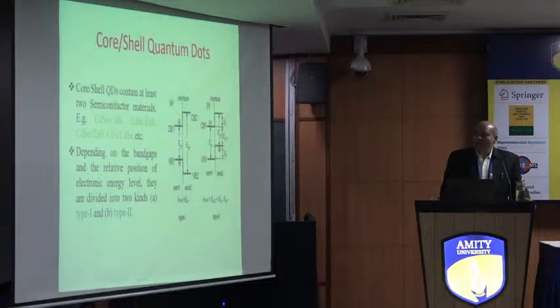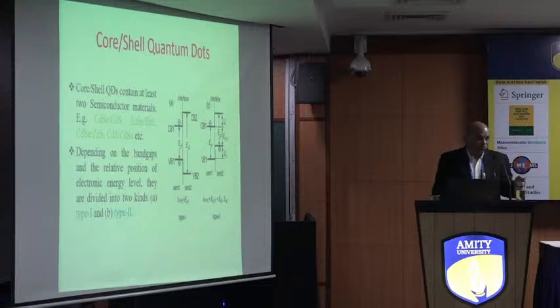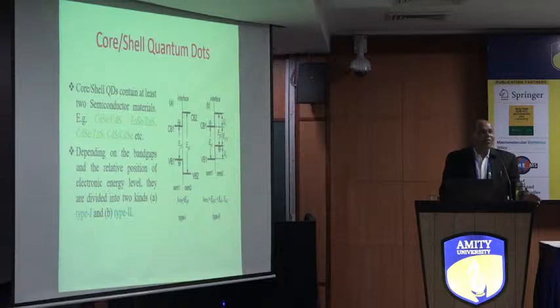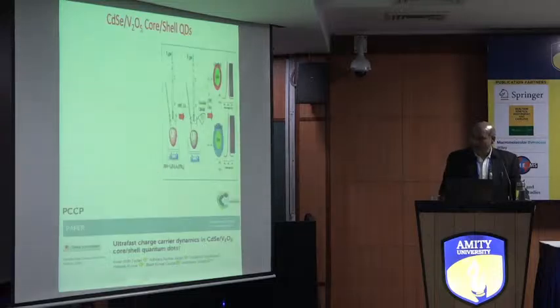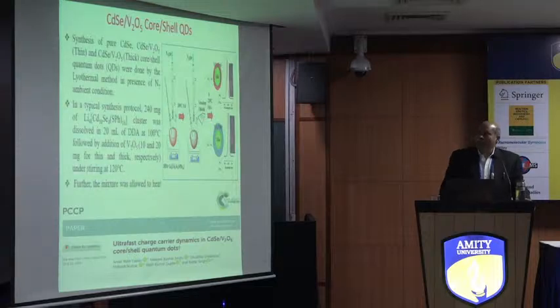Other is the core shell quantum dot. When you take two quantum dots, one can be the core and the other the shell. Then what will happen here? The property will be changed. And second, the stability of the quantum dot will also increase. So I want to show you, we prepared CdSe/V2O5 core shell quantum dots for different concentrations. Here one is for thick and thin, then we give some names here.